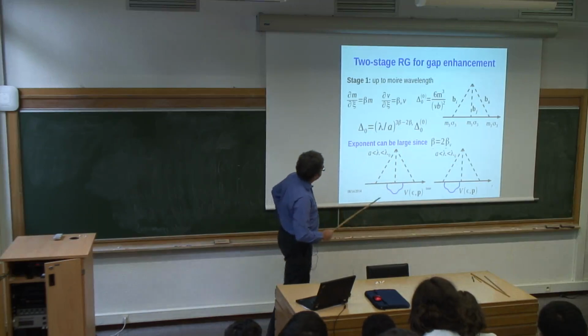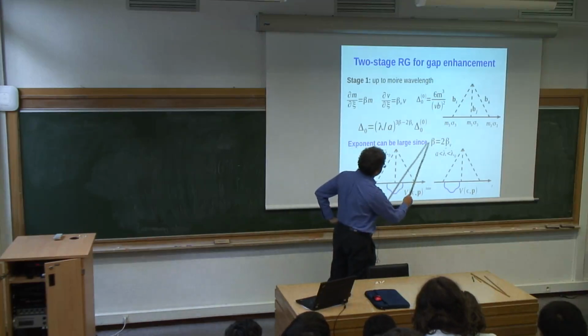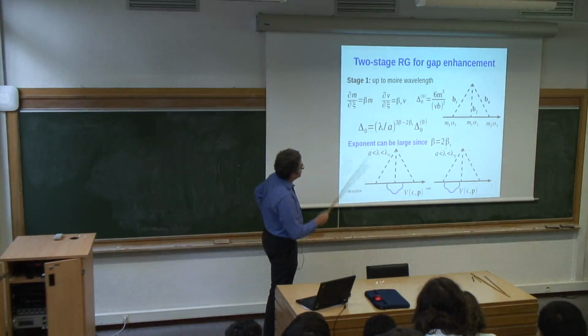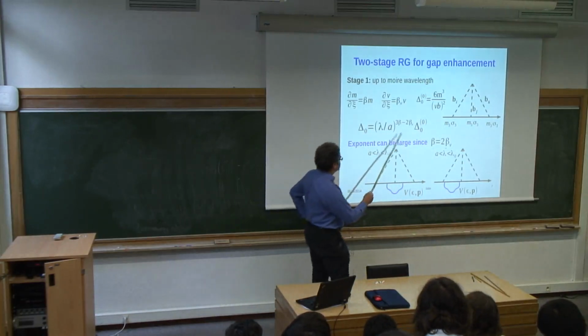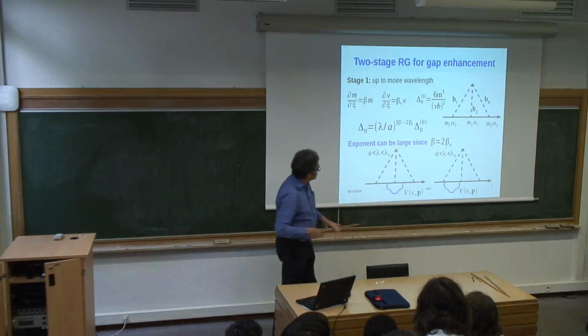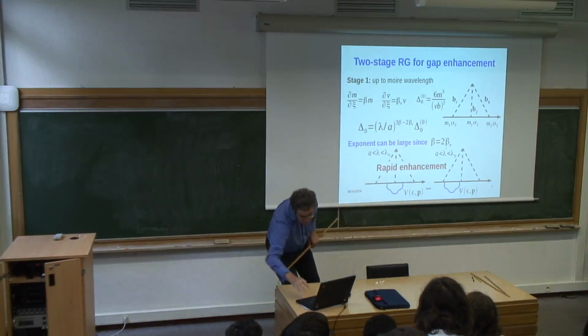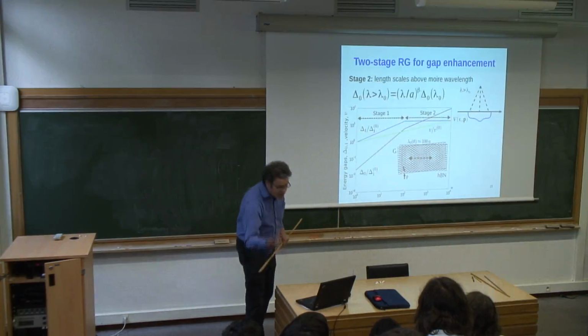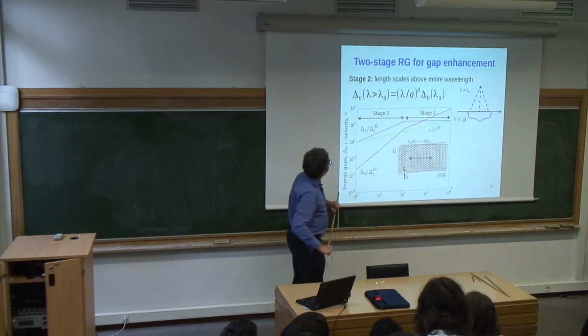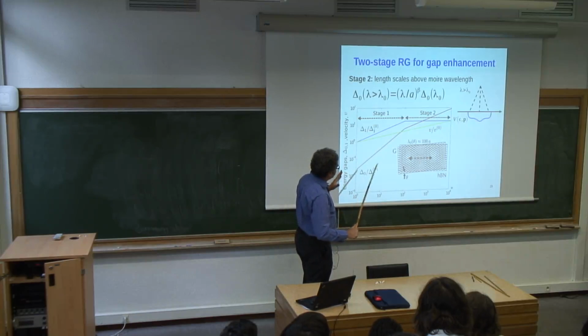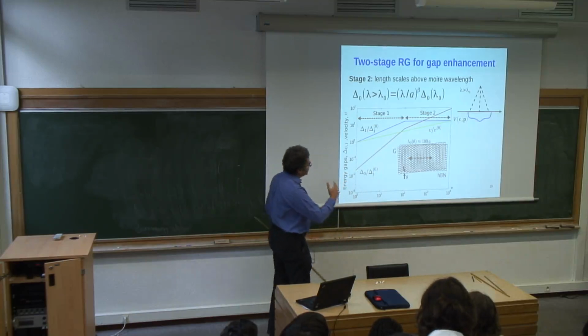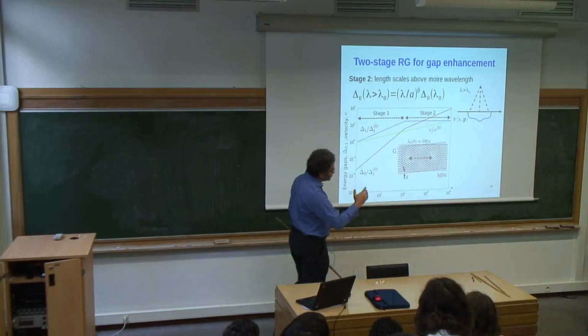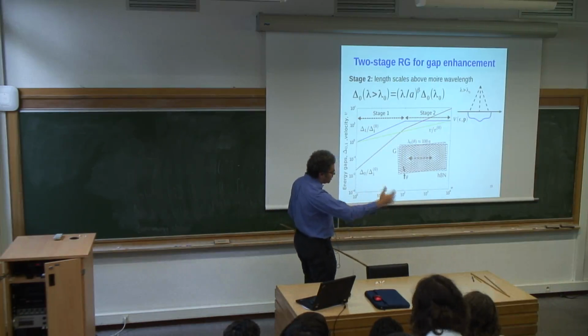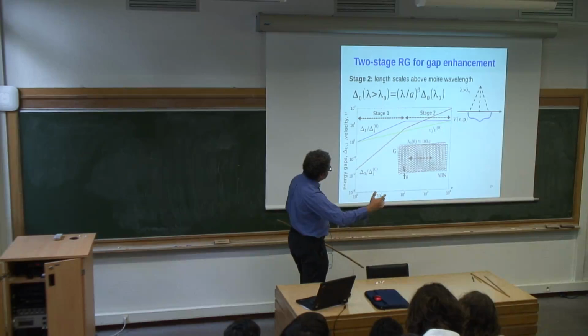And then because there is this factor of 2 difference between beta mass and beta velocity, there is some combinatorial factor that produces a fairly sizable exponent and a rapid enhancement. And then, if you want to make a complete story out of it, you have to think about what happens at different length scales. For example, what we said in the previous slide was good at length scales from lattice scale up to the moiré superlattice scale, and then if you go beyond that, then your particles